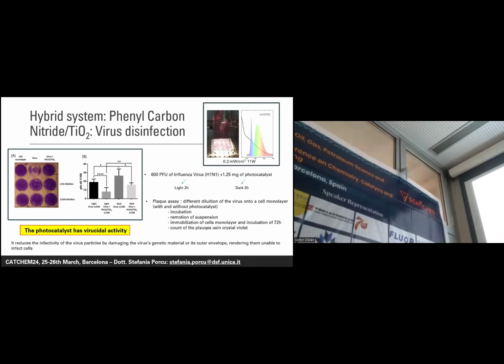Then we did a plaque assay using different dilutions of the virus and a cell monolayer to test how infectious the virus is for the layer. And even here, after the incubation process, we tried to underline the results using crystal violet, that is a dye that allowed us to color the monolayers of the cells, and the results are shown here in the slide. So in the first column, you can see the cell monolayer that we kept as control test without virus and without photocatalyst. The second column was the vitality of the cells when they only interact with the virus,